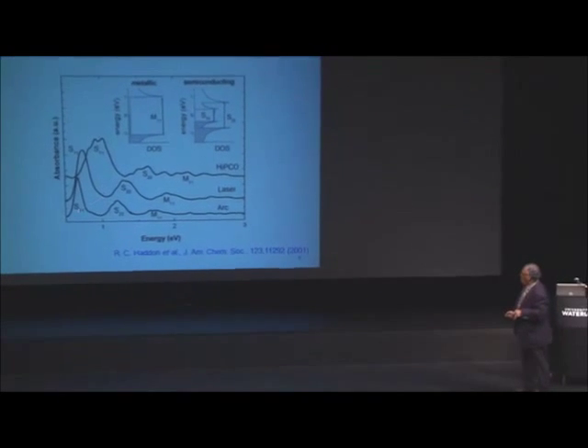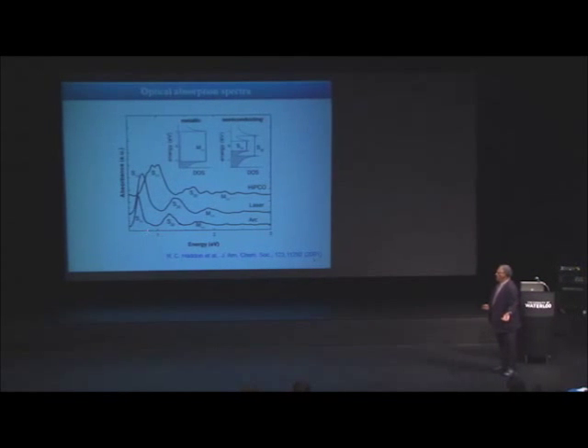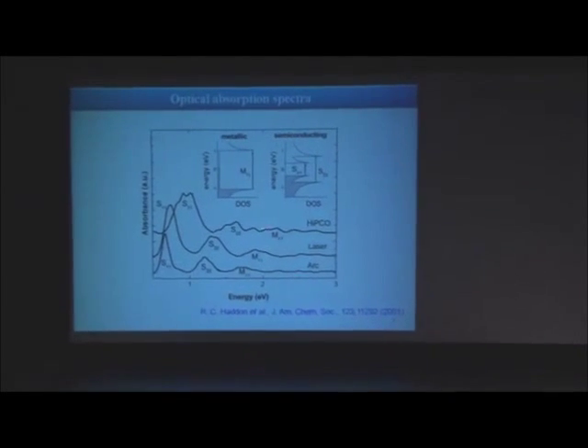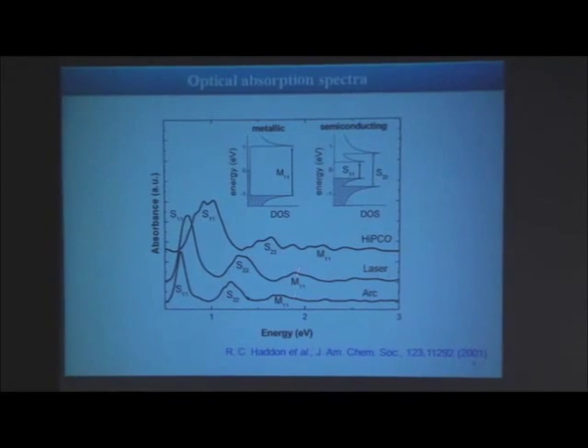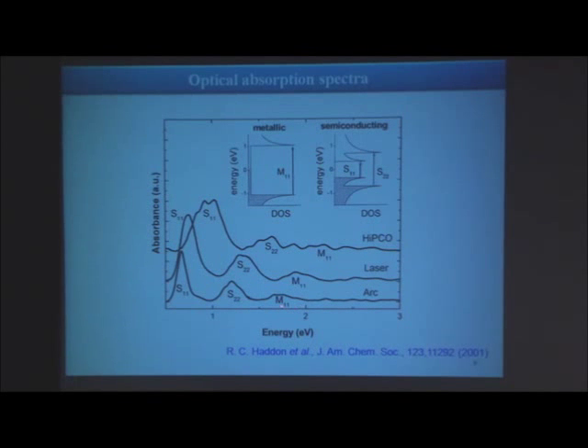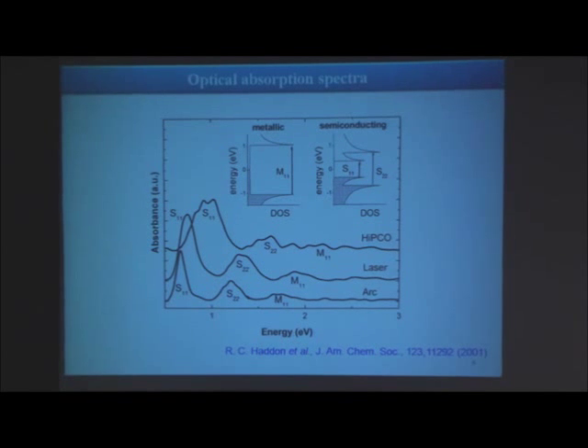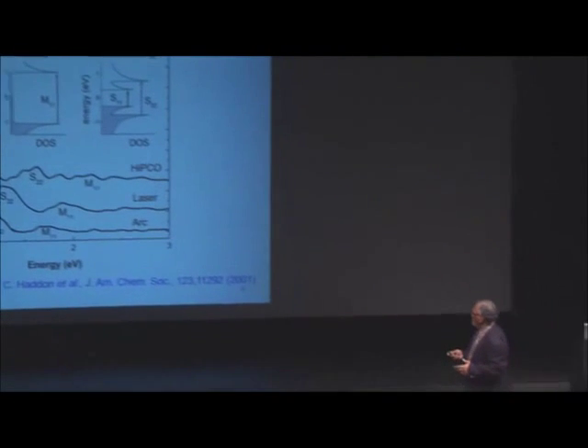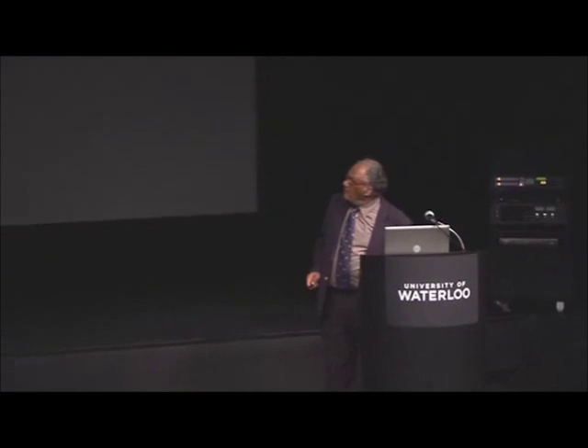Another important characterization, again, which I'll be using later, is the electronic spectrum, or it's really the near infrared and visible region. For example, this is in electron volts, don't worry. Here, there are characteristic bands due to the metallic species, around 500 or 600 nanometers, and around 1,000 nanometers here, there are bands due to the semiconducting species. And these are all arising because of the so-called van Hove singularities in the electronic structure of nanotubes. So we'll be using this quite a bit to understand whenever we deal with nanotubes.